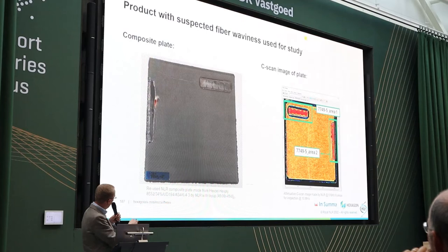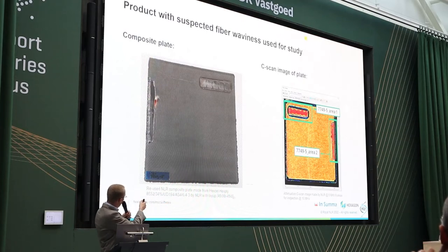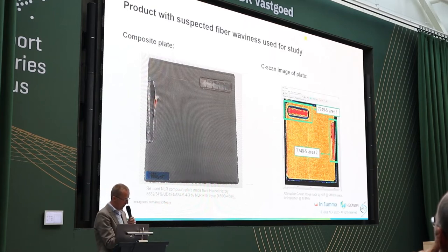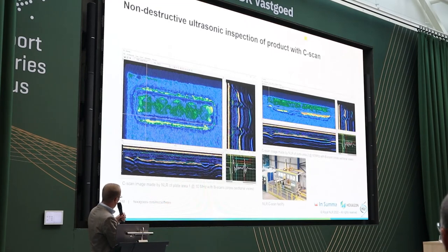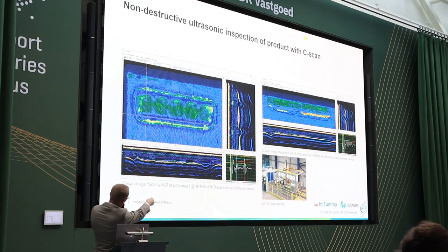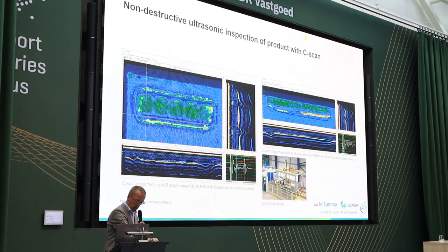So we made a C-scan, you see the image on the right. You can really see the two areas where the fiber waviness is, but not the amount of fiber waviness. We could not see it yet. For this, we used another ultrasonic transducer with higher resolution, not 5 megahertz but 10 megahertz. Then in those two areas of the plate, you can see the B-scans on the left and on the bottom of each area. You can see the fiber waviness. Also, I have a part of the plate with me, so after the presentations, those who are interested can see the plate and the coupons.